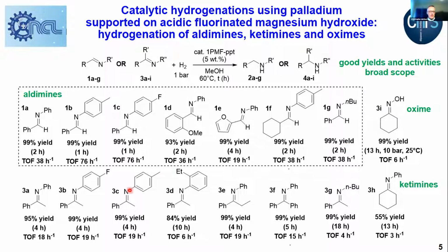And ketimines are also effectively hydrogenated under 1 bar hydrogen with almost quantitative yields, but in a few hours, 4 to 18 hours for more difficult substrates.